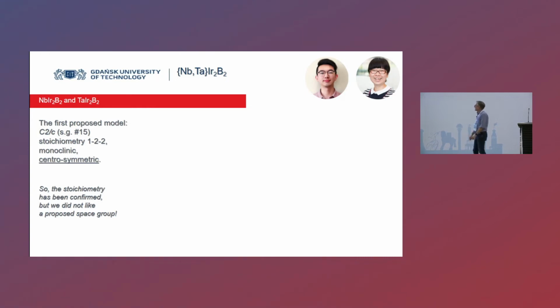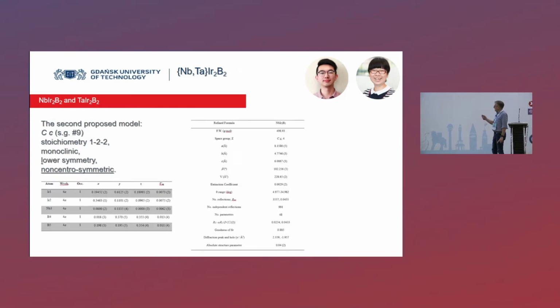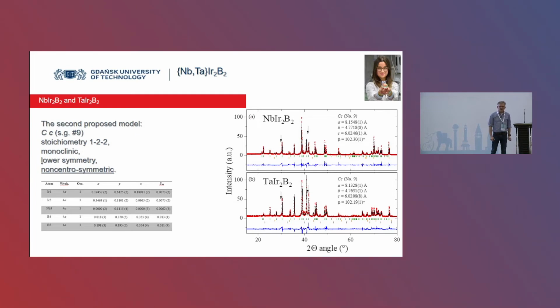So we asked for another model, and the model which came to us was one in which the space group is even lower. It's number 9. So monoclinic, still monoclinic, and non-centrosymmetric. And that one, as you can see, worked out. So it works like that. Without the crystallographers, you cannot go to the next level. But when you get the crystallographic table, you have to go back to your powder X-ray diffraction and try Rietveld analysis. And Karolina Górnicka did this, and you can see it's pretty much what you expect. There are some small impurities, but this is confirmation of the crystal structure.